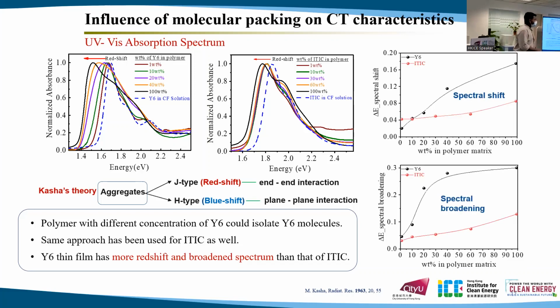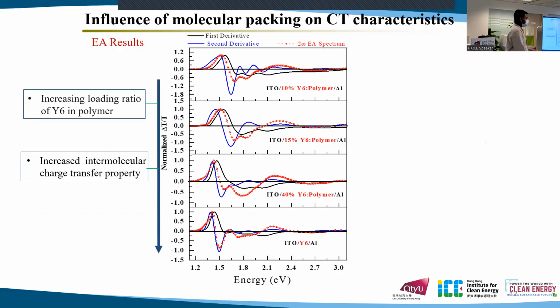And from this figure, we can see Y6 has more redshift and spectral broadening compared to ITIC. That indicates that Y6 has strong molecular packing compared to ITIC, as shown by different dimer configurations. So now the samples are ready. We can go to the EA results, and these are the most important results that we got during this research study. We can see the increased concentration of Y6 in the polymer. This is 10% Y6, 15%, 40%, and this is 100%.